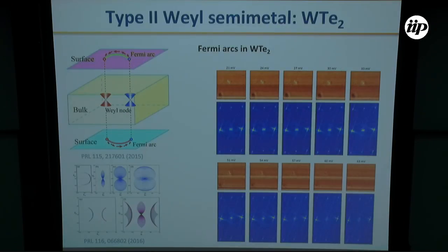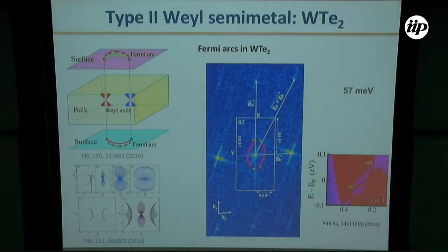When we look at the QPI signal produced by the other type of defects, essentially what we obtain is information from the topological state at the surface. The QPI signal expected from one of these Fermi arcs is a feature with an 8 shape. When we look at the QPI signal, we find the appearance, I don't know if it is clear here on the screen, of this 8-shaped feature in the Fourier transform at an energy between 50 and 60 millielectron volts. This is a clear signature of the presence of the Fermi arcs, and they appear at the energy where band structure calculations predict the appearance of this Fermi arc, and also at the position of the projection of the Weyl point on the surface.